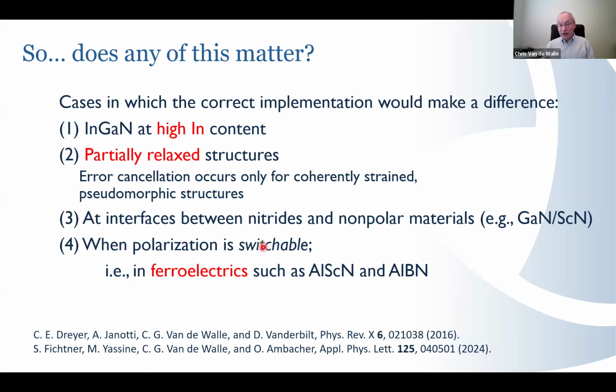And then there are the situations where you really should be using the correct absolute value of the spontaneous polarization. Clearly, this is the case when you're dealing with ferroelectrics, because the zinc blende values for spontaneous polarization just do not make sense. But it's also the case if you want to look at interfaces between nitrides and nonpolar materials. And I know at Cornell, there is a lot of interest in those. For instance, gallium nitride, scandium nitride interfaces. Scandium nitride has zero macroscopic polarization. It has a rock salt structure. You form an interface with wurtzite, you're going to get the polarization discontinuity. You need to use the value referenced to the layered hexagonal structure to correctly describe that.